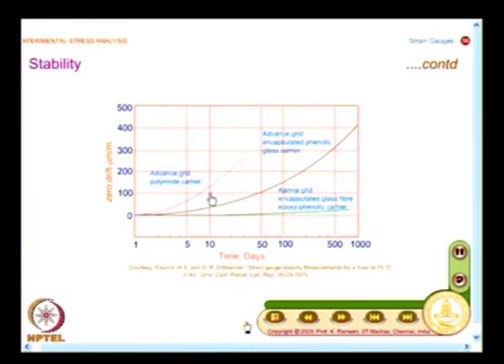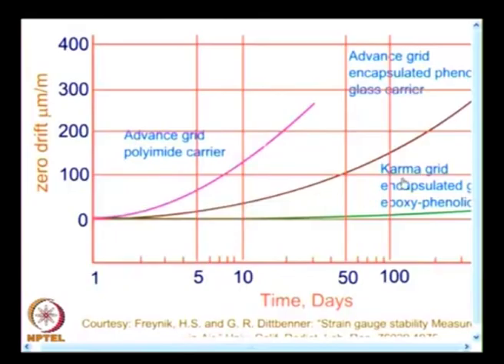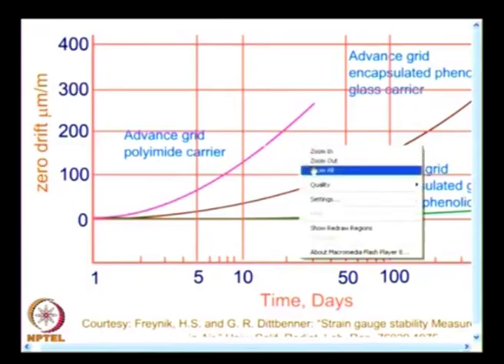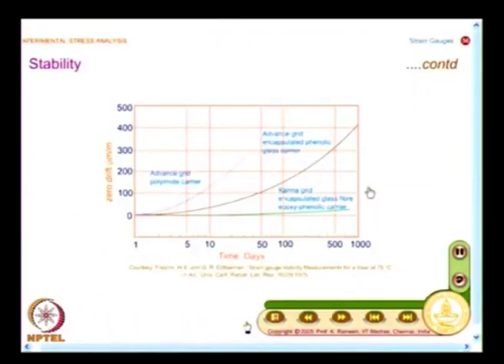So, what you find here is by changing the strain gauge alloy, finally the system as a whole has improved. From the first graph to the second graph, you found that the carrier has indeed improved. A further improvement is possible by changing the alloy itself. So, that is where I said you need to look at the strain gauge as a system, and you have a summary of the observation of the graph, which is available in the next slide.